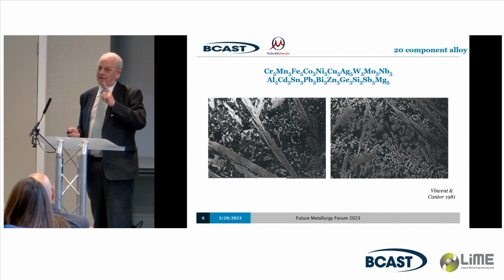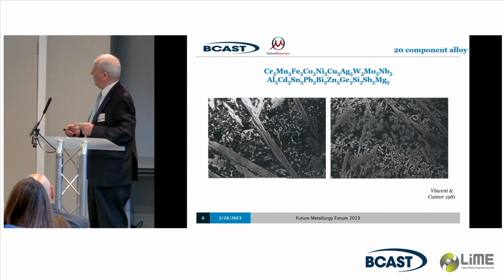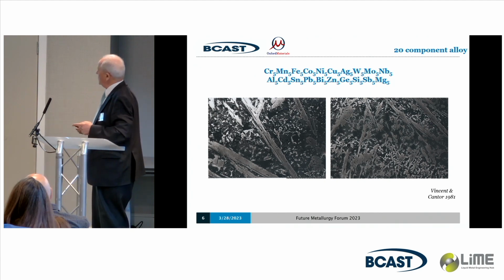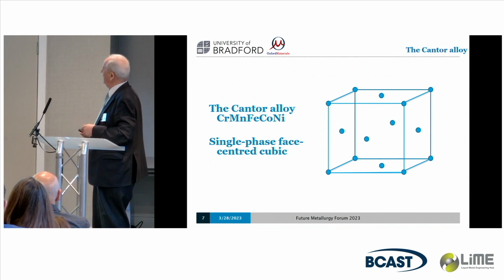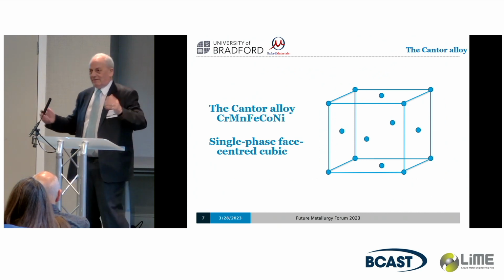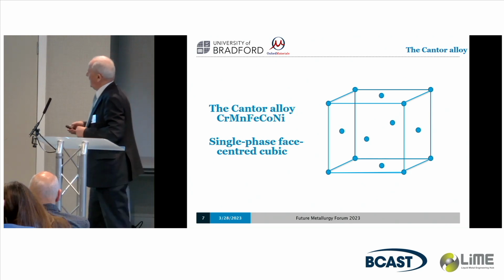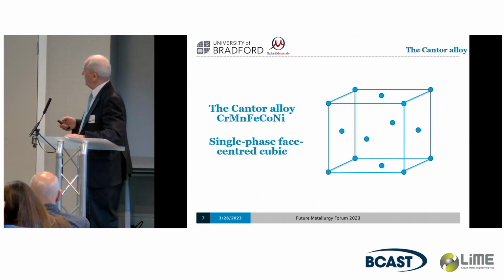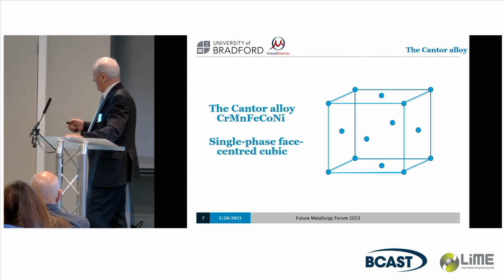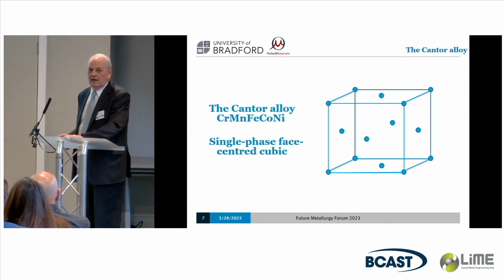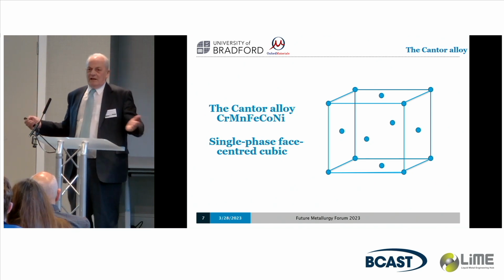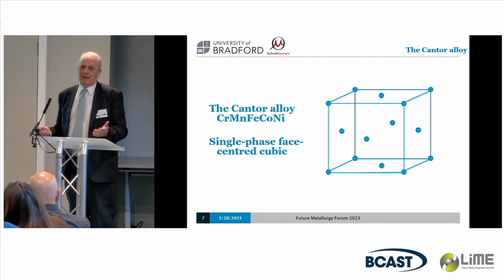But the second thing we discovered within about 3 days was they were wrong. Because this black phase here turns out to be what's now known as the Cantor alloy. I didn't give it the name, so don't criticise me for self-promotion. I think Rob Ritchie is the one that first used the name, but anyway, it's widely used now. And it's this material here. It's 20% each of chromium, manganese, iron, cobalt, nickel in equal proportions, and it's a perfect single crystal material, single phase material of a face-centered cubic structure. And it was a complete surprise, utterly amazing that should happen.